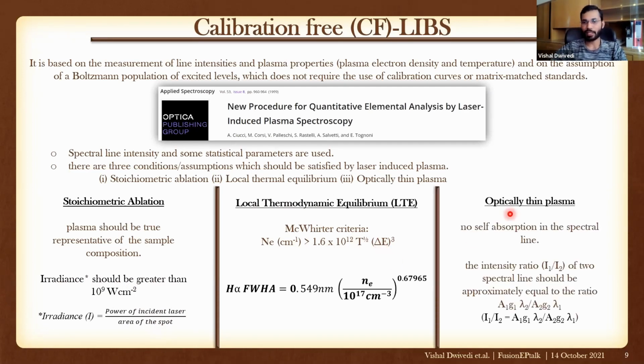And this is optically thin plasma. For this, we should verify there is no self-absorption in the spectral lines. And for this also, we have one criterion. The spectral lines intensity ratio of two spectral lines should be approximately equal to the ratio of this, where A1, A2 are Einstein coefficients, G1, G2 are g factors, lambda 2, lambda 1 are wavelengths.